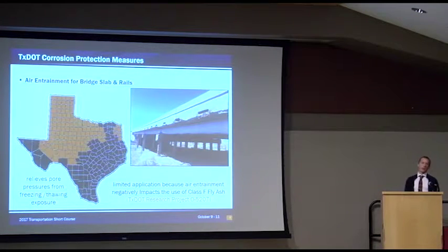Now, another thing we do is air entrainment. We all know about freeze and thaw cycles in the northern part of the state. Air entrainment helps us to avoid cracking from those stresses because cracking would allow the chlorides to come in faster. One thing I'll mention about this is that we do like our Class F fly ash. We like air entrainment. But Class F fly ash and air entrainment don't get along together. When Class F is in the mix, it becomes kind of difficult to hit our target air content. So we don't specify air entrainment statewide. We limit that to the northern parts of the state where we really need it.